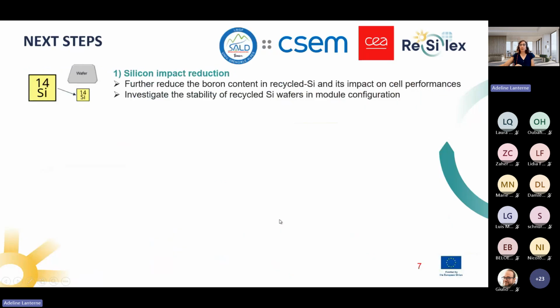If now I say a few words about our next steps concerning the silicon impact reduction, due to the fact that we have more impurities, as I said before, in these materials, we have a specific issue with the boron content, which is very high in this recycled silicon. So the next step could be to further reduce this boron content in the recycled silicon, or to improve the pre-treatment that we have developed in the project to reduce even more the impact of this boron on the solar cell performance and especially the solar cells stability under light.